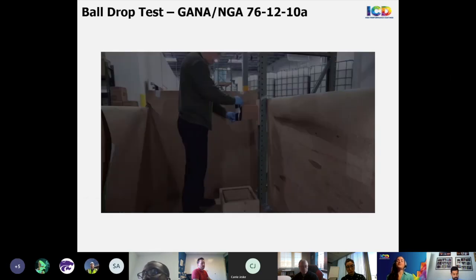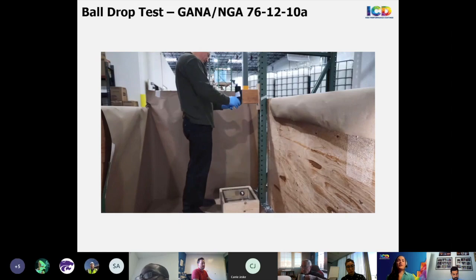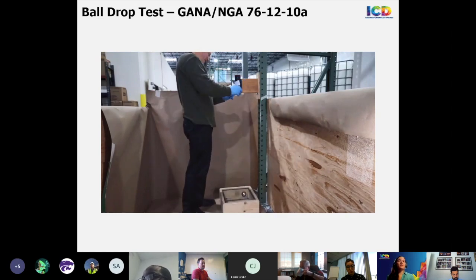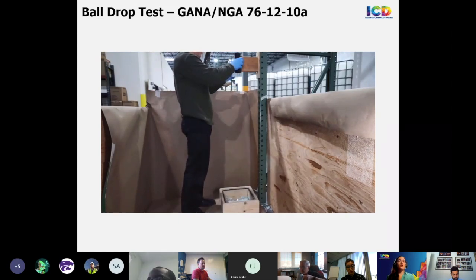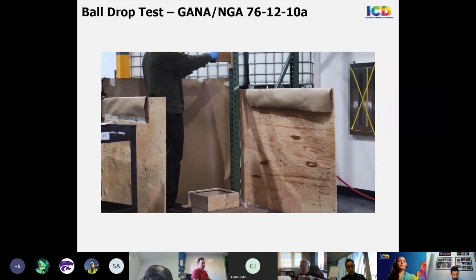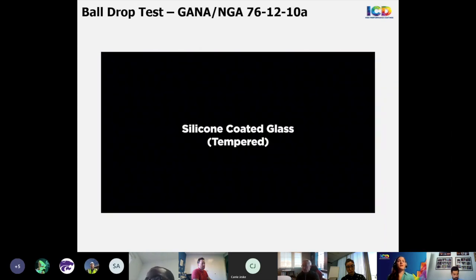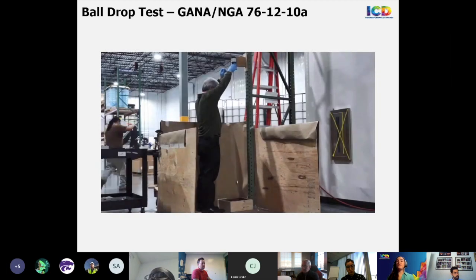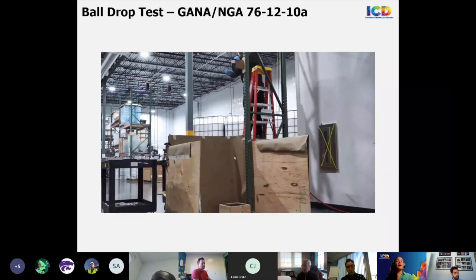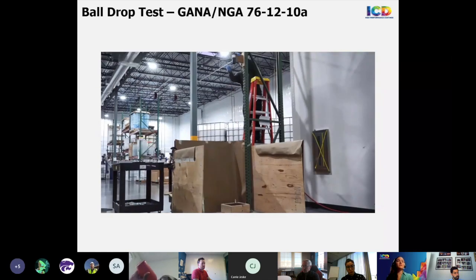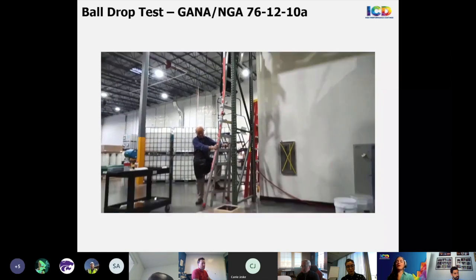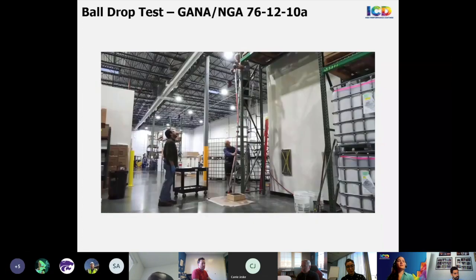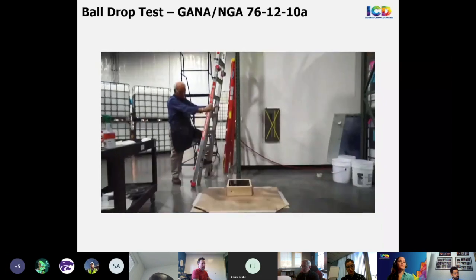So I'm actually going to show a fun video that demonstrates the results of this testing. So first, clear uncoated tempered glass was tested with increased height, and breakage occurs at about 4 feet. Next, the test was repeated on tempered glass with the silicone coating alternative to Frit applied after the glass tempering process. And you can see the silicone coated glass achieved much greater heights. I believe in this testing it went up to about 11.5 feet.